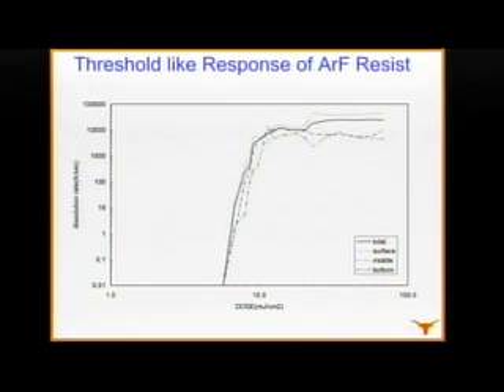So just to show you that that's a cartoon, these are real data. Here's a modern resist. Shine light on it, nothing happens, nothing happens, nothing happens, nothing happens. And then suddenly, over a distance of only a couple of millijoules per centimeter squared, it switches 5 orders of magnitude in dissolution rate. That's a remarkable thing to have happen. And it took quite a while for people to learn how to make that happen. Anyway, this switching point, everybody calls E0. I don't know why. You could call it anything you want.